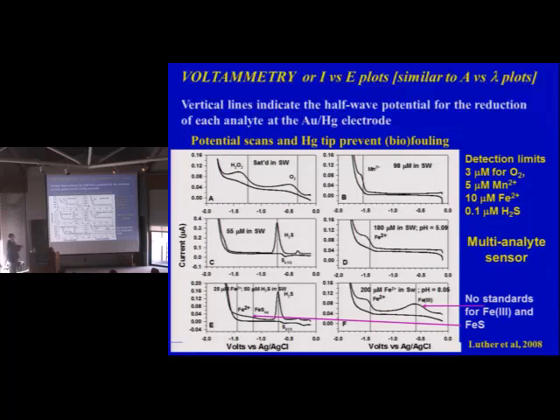One other thing is you'll notice that we go off scale on a couple of these at the end at minus 1.8. We actually go into the sodium ion wave if we go in too far. and the sodium ion reduces the sodium amalgam, and then that generates hydrogen at the electrode, and that actually helps clean the surface. So we can actually clean these after every scan by scanning into the sodium wave. Same thing happens in fresh water. If you have potassium, calcium, magnesium, the same thing happens. So this is one of the ways that we clean the electrode. And there's other ways we can condition the electrode in between scans so that it comes back to its original condition. So these can go easily 20,000 scans, over a period of time.